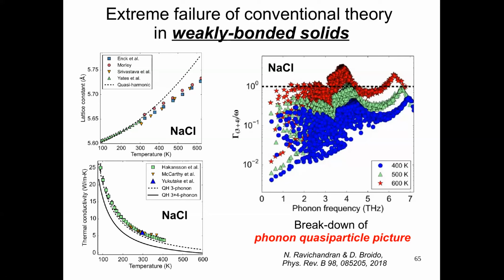That was a good question. So yeah, if you take a very thin material sample, for example, you will have boundary scattering. So this 4-phonon scattering can be treated on the same quote-unquote footing as 3-phonon scattering, in the sense that you can calculate an effective mean-free path combining both 3-phonon and 4-phonon scattering rates. And if that mean-free path is comparable to your system dimension, then the diffusive scattering at the boundary becomes important. So it's really a comparison between the length scale of your sample, temperature as another variable, and the material that you're using.